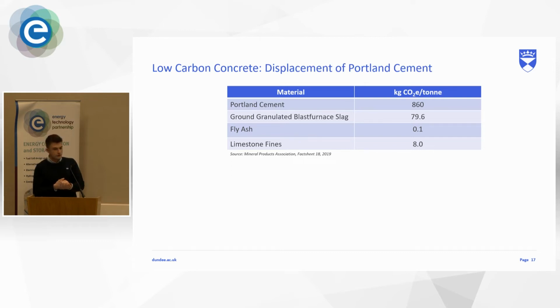Then we have low carbon alternatives of cementitious materials, which are granulated blast furnace slag, or GGBS for short, fly ash, and limestone fines, which are all essentially waste byproducts of steel production, coal-fired power stations, and limestone processing, respectively. And therefore, you can see that the CO2 footprint associated with these materials is quite low, because it's associated with the actual primary product rather than the waste byproduct.